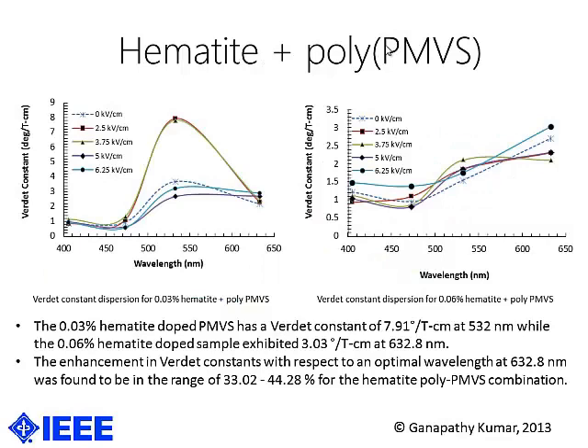Now, when we looked at the first set of samples that were doped with hematite and poly-phenyl methyl vinyl siloxane, we looked at the wavelength dispersion of the Verdet constant, and we noticed that for electric fields of 2.5 kilovolts and 3.75 kilovolts, at around 530 nanometers, we were able to get a peak Verdet constant, and anything beyond that, the Verdet constant just kept decreasing. So for the 0.03% hematite, the Verdet constant was measured at about 7.9 degrees per Tesla centimeter, and the 0.06% hematite doped sample showed 3.03 at 632.8 nanometers. That was like a linear shift. I mean, it came down by half almost.